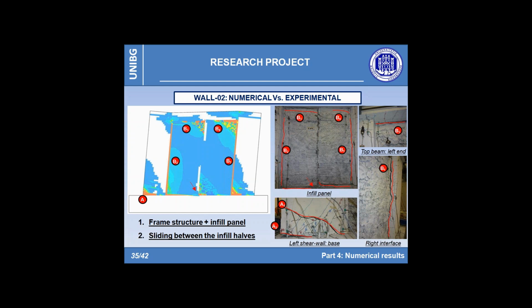Thanks to the presence of the central interface, the simulation has been able to reproduce the sliding phenomenon that occurred between the infill halves, as highlighted in the picture with the red arrows. In this way, the infill tends to become inactive very quickly, and vertical and horizontal cracks appear along the perimeter of the panel.